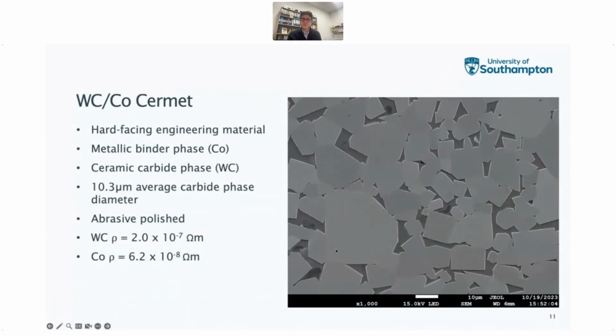The second material was the cermet. This was abrasively polished, and you can see the darker binder phase, the cobalt phase here, for example, and the grains, which had quite a distribution, but an average size of around about 10 microns each.